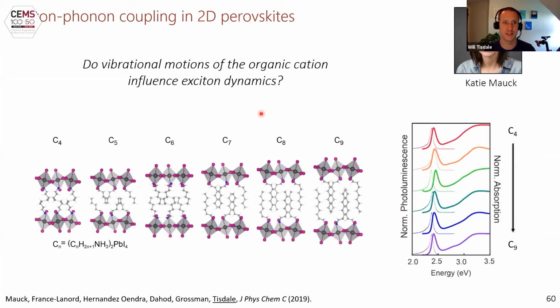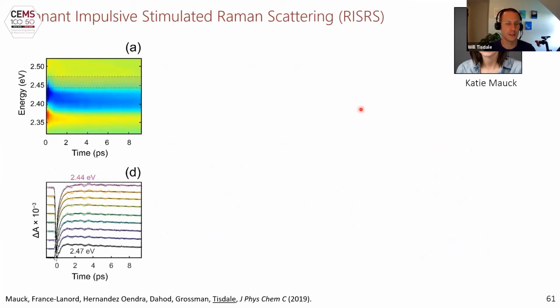We wanted to see if that extended to vibrational properties as well. Katie, who's now a professor at Kenyon College, synthesized a whole series of N=1 lead iodides with variable length alkylammonium ligands. You can see from the optical emissions absorption spectrum that the band gap is not changing. The only outlier here is the C6, which has a different symmetry than the other 5 members. Katie did some great work.